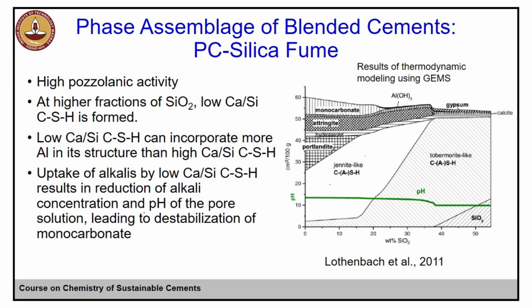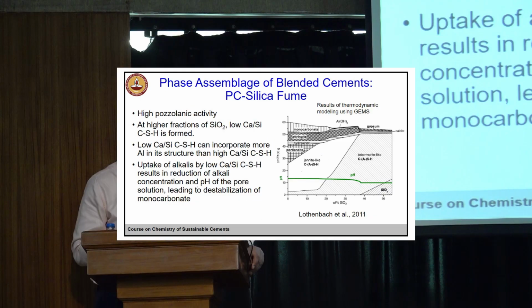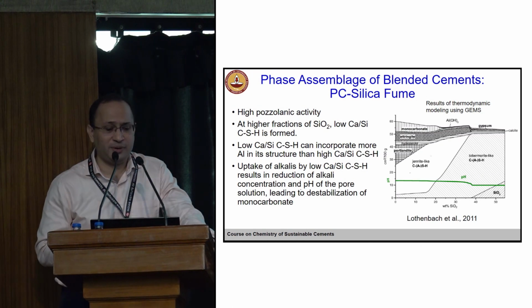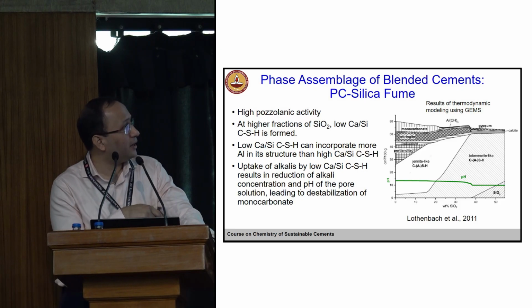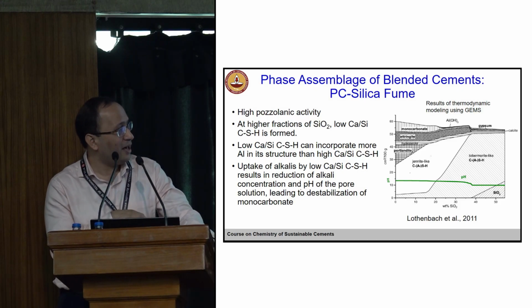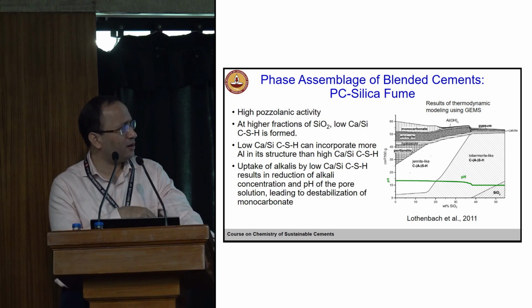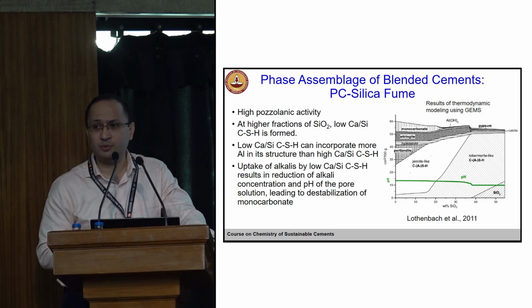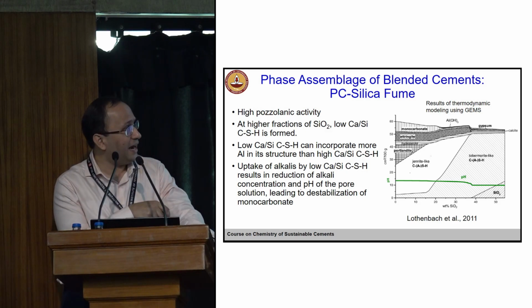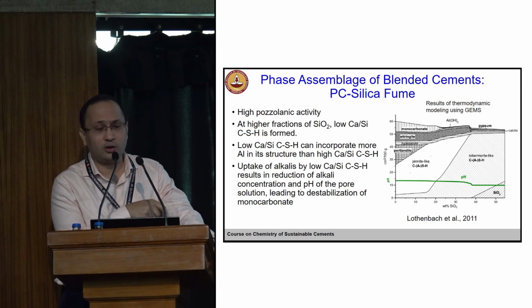Now silica fume is obviously a more reactive material. We'll come back to the reactivity assessment later, but typically it has very high specific surface area, very fine material. It's supposed to have very high reactivity. Similar kind of thing you see here, but compared to fly ash, at smaller percentage you can see a transition to low calcium to silicon ratio CSH. And it consumes the portlandite also very fast.